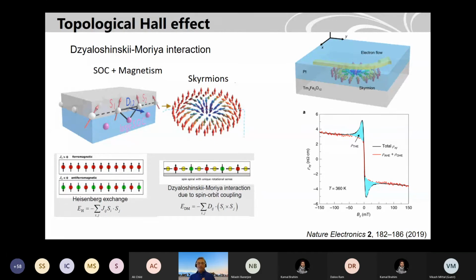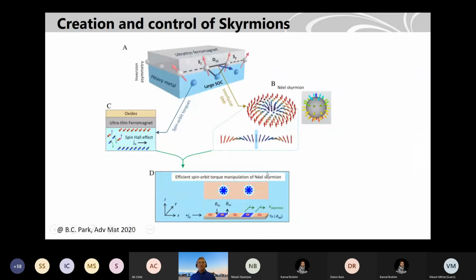Then you have the anomalous Hall effect when you apply a magnetic material in the system. Then you saw the spin Hall effect comes from the spin orbit coupling, and the topological Hall effect comes when you have both magnetism and spin orbit coupling. It gives rise to these new magnetic structures called skyrmions, and they are actually topologically protected, so you cannot destroy them simply. So this gives rise to this topological Hall effect. So these are very new developments in the field of spintronics.